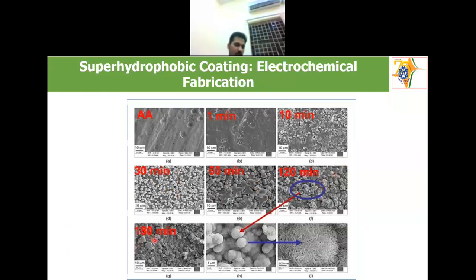At 180 minutes, what is happening is that with the high potential and more time for the deposition process, a kind of charging happens. That is why the contact angle decreased also. When you enlarge this area, we are able to find that each of the spheres is almost 1 micron in size.